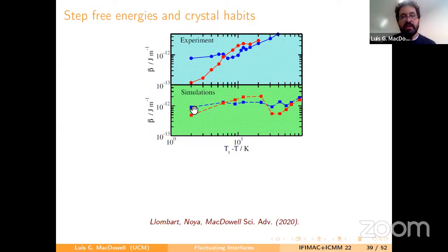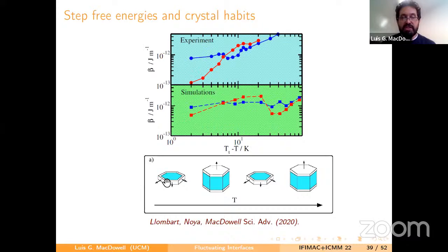And so we see that close to 0 degrees, the step free energy of the basal phase is higher than that of the prism. So what that means is that the prism phase is going to grow faster. And if it grows faster, it's going to make plates. But then if we decrease the temperature further, then suddenly it is the prism phase that has larger step free energies, which means that the basal facet is going to grow faster. And then you get columns. And then further decreasing the temperature, the basal phase gets larger step free energies, and then the prism phase grows faster and you get plates.